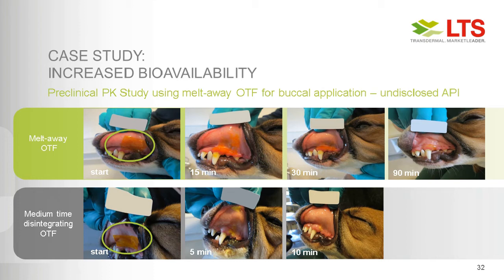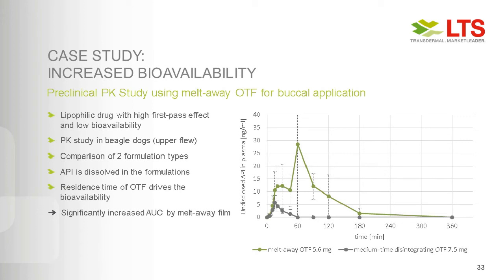just by the tongue. The bottom row is a formulation which is not a fast disintegrating film, a medium time film, I would say, which does not disintegrate within seconds, but within a few minutes. And you can see, starting with this orange film on the mucosal tissue, within 5 minutes only small pieces are remaining, and after 10 minutes everything is gone. And by these different disintegration times and residence times on the mucosal tissues, we could achieve in this feasibility study different PK profiles. And these were the results here of the PK data of this API.